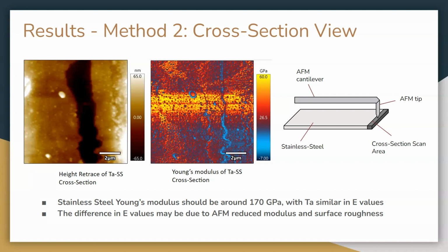And the lower Young's modulus may be due to reasoning such as at the interface, it's super hard to find where the tantalum actually is. And then the difference in Young's modulus values between experimental and theoretical may also be due to the fact that the AFM measures reduced modulus and that may result in lower Young's modulus values.